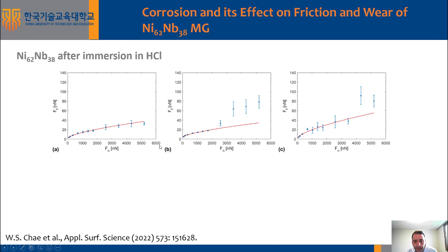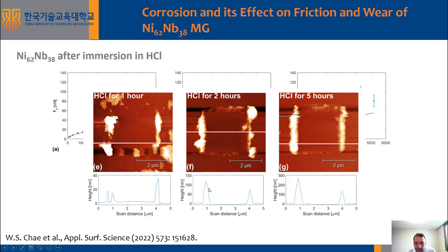And correspondingly, we also find here that the pileups after 1 hour in hydrochloric acid are rather low. We do find some increase in pileups after longer immersion into hydrochloric acid. However, it rather looks like we are smearing the oxide on the sample surface as we would smear butter onto bread.